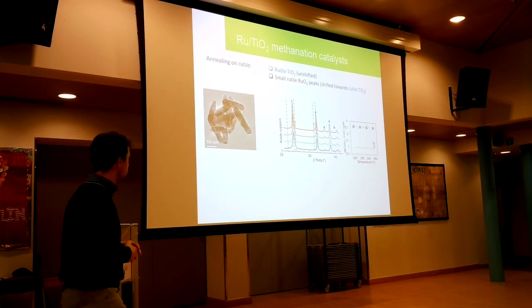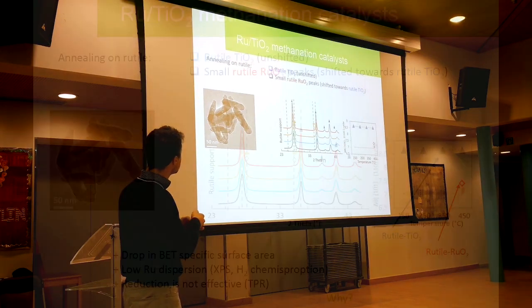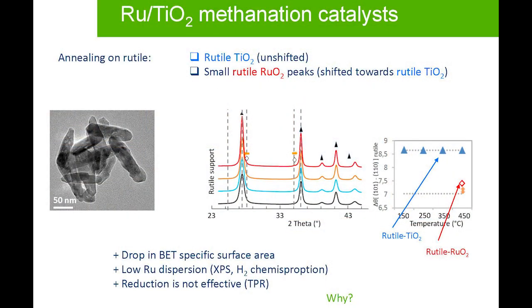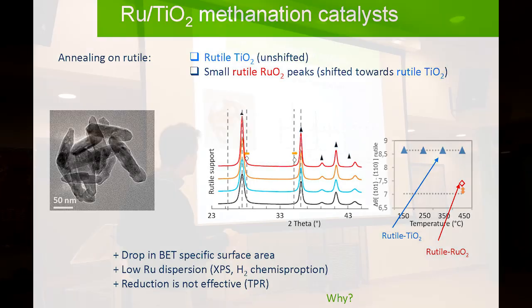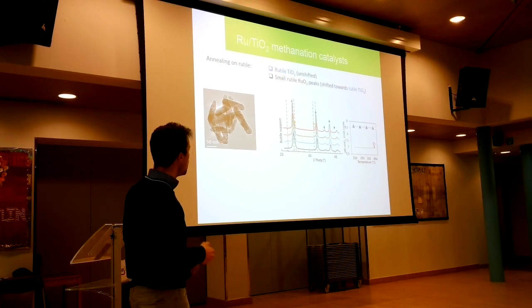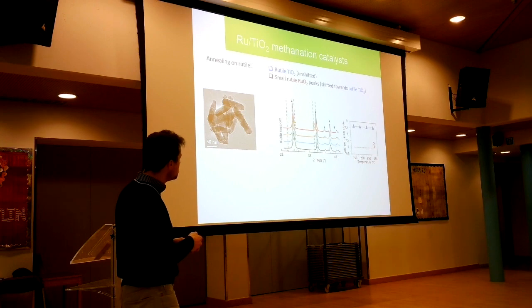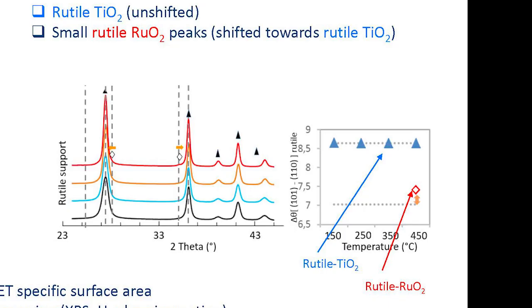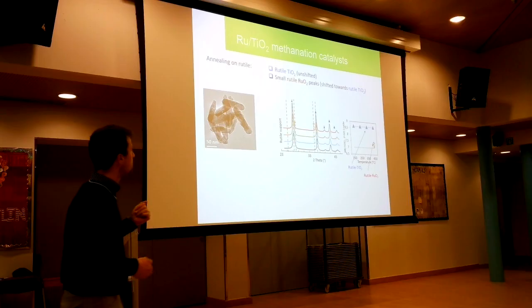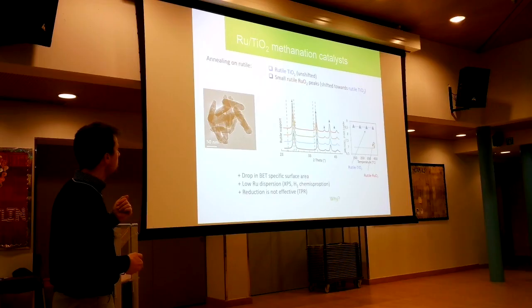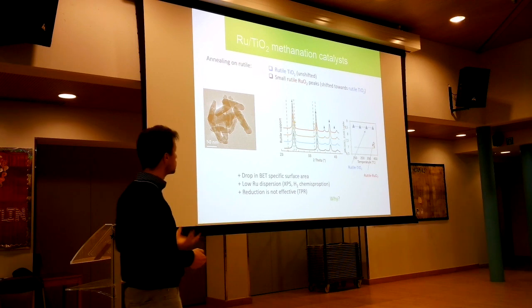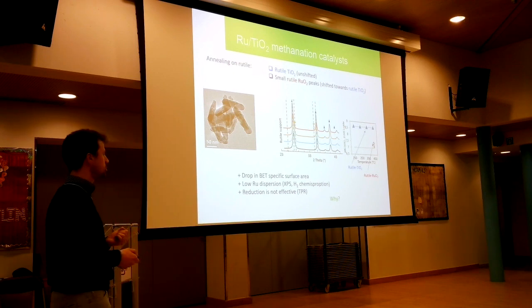So what's happening on the other supports? For rutile, in this case, we also have the expected peaks. Those triangles there belong to titania rutile, and they land on the expected position. Again, at low temperature, we don't see the ruthenia, but here at high temperature, we start to see a tiny little peak here. And what we notice is that it did not land on the expected position. It landed a little bit higher, and this was also a bit intriguing to us.